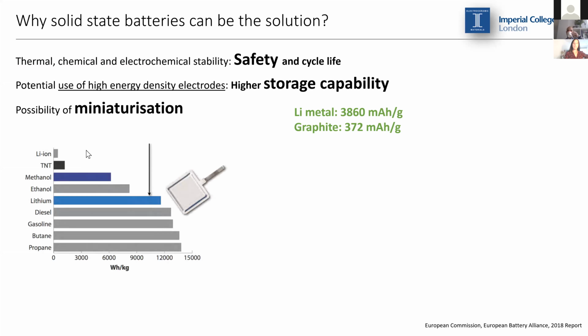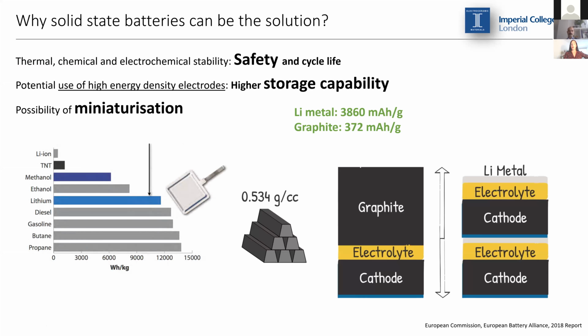If you look at this figure here, you can see that actually the energy density of lithium metal is in the same order as that of the fossil fuels. So the range of applicability to higher energy density applications increases a lot. Also, lithium metal is very light, and we can stack cells more easily, and therefore we can achieve higher energy densities for the same volume.